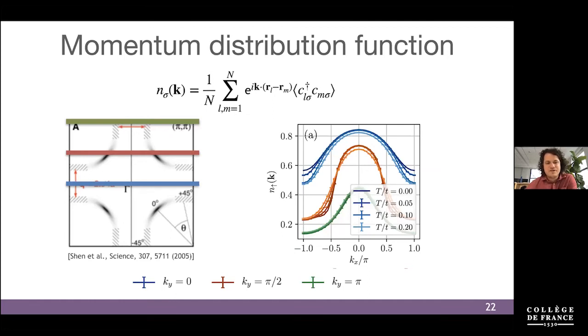But let's go for the key feature of the pseudogap phase. Is there actually some spectral suppression on the boundary of the Brillouin zone? This is what we want to capture by looking at the momentum distribution function. Whenever there's a Fermi surface, so a gapless mode, the momentum distribution function should have a discontinuity. This is known from Luttinger. We evaluated the momentum distribution function both at zero temperature and also at finite temperature. At zero temperature, it holds that the momentum distribution function should have a discontinuity whenever there's a gapless mode.